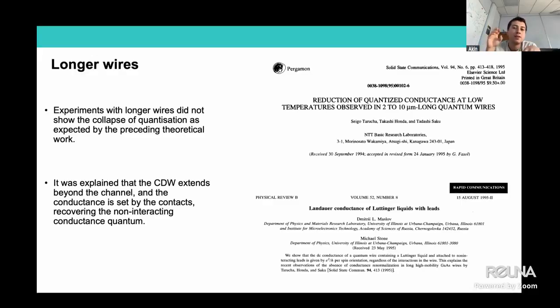And the conductance that we have, the 2e squared over h, where 2 stands for spin degeneracy, by the way, so that's e squared over h for each spin channel, is defined by the contacts, because the outside of the one-dimensional system is still a Fermi liquid. Of course, we see a modulation to this conductance quanta in things like the fractional quantum Hall effect, but this was not observed in these long wires as people initially thought.